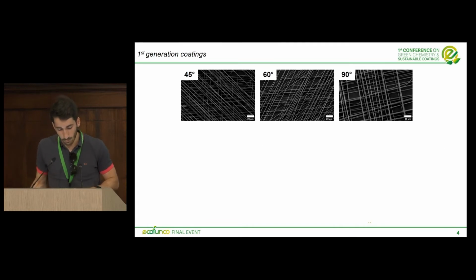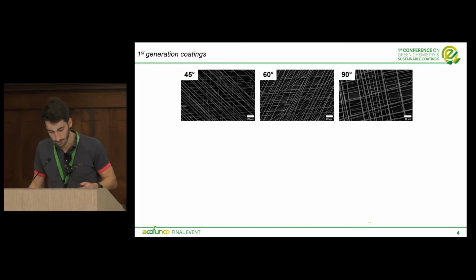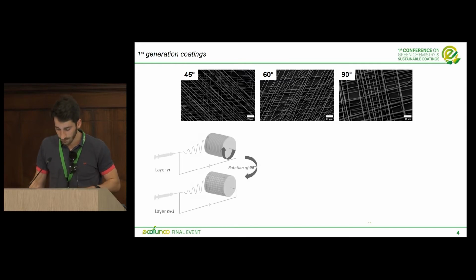So at first, we produced what we call first-generation coatings that consisted of up to 4 layers of aligned PVDF TRFE, a piezoelectric polymer, a copolymer of PVDF. So we have produced these coatings up to 4 layers of aligned fibers with alternating orientations with 45 degrees, 60 degrees, or 90 degrees. To collect different layers, we have adopted what we have called a number layer step procedure